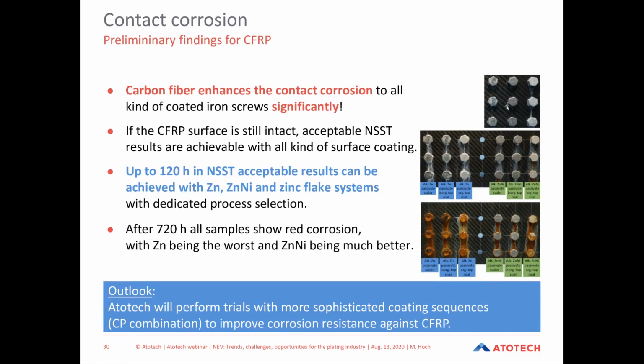So to summarize our preliminary findings for contact corrosion with carbon fiber: carbon fiber enhances the contact corrosion of all kinds of coated iron screws significantly. If the carbon fiber surface is still intact, so when the epoxy is not scratched or defected, then we get acceptable neutral salt spray results with all kinds of surface coatings.